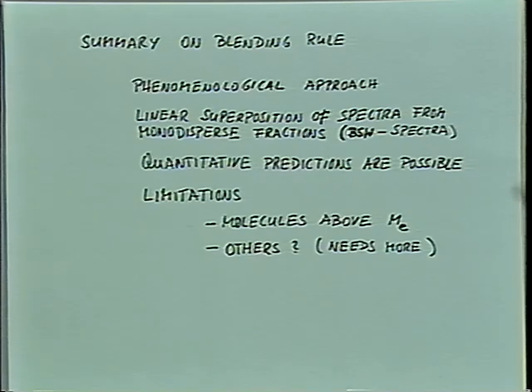The limitations are, the biggest limitation is that all the molecules should be of sufficiently high molecular weight. We should not have molecules below the entanglement molecular weight, otherwise our broadly distributed system would be plasticized and the whole spectrum would be changed. Just remember the data in polymer solutions, taking a monodispersed polymer in solution and how the addition of small molecules changes that spectrum so drastically. Now imagine you have your complicated spectrum, like here for the polymer blend, and then have a solvent effect in this case. It would be very, very hard to analyze.